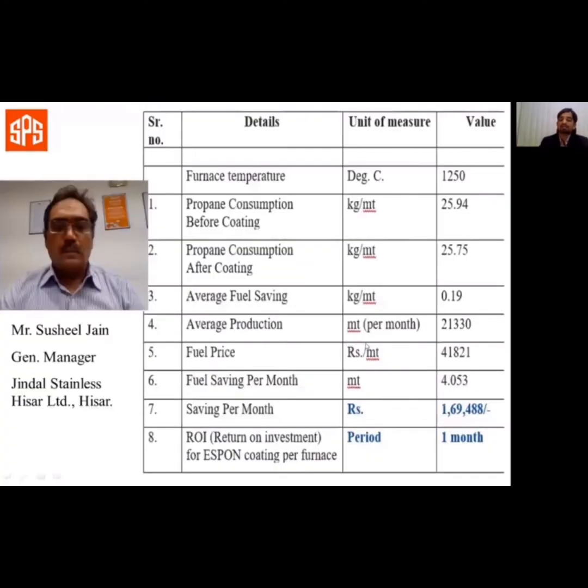And finally, my last case study, which is actually a worst case scenario. Ironically, it is also one of the best case studies that I have to present here. At Jindal Stainless Hisar Limited, they have highly efficient furnaces designed and supplied by Andritz, Germany. Very fuel efficient. The outer shell temperature is not more than 45 degrees Celsius. No problem of refractory or any other issue whatsoever. The only reason the coating was tried here was with the aim of reducing fuel consumption.